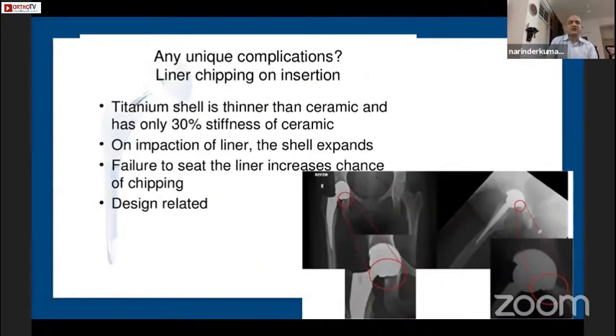And then this is something which I've revised for, the liner chipping on insertion. I've had patients coming to me where the index surgeon forgot, or rather ignored, that the liner had not been seated completely. That happens, one, because there's a taper junction issue. Secondly, there's a malposition, a surgical technique challenge. Or there's a manufacturing issue also, that when we are impacting the liner in, the shell expands and the taper junction is not adequate to cater for that expansion. So when the patient starts walking, there is a chipping of the edge of the liner. This is basically a design related issue, as I said.